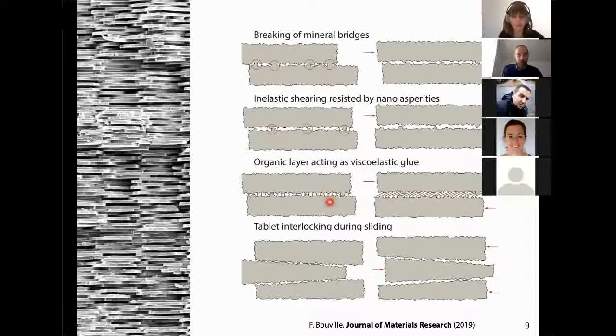And finally, if you look just at the interface, you also have this organic layer that will just act as a glue, right? And so in shear, you're going to have to shear the polymer, the protein layer as well, when you're trying to deform it. Finally, something that is also present in the structure and has been looked at is that it seems like there's an interlocking mechanism during sliding. So you can see that some of these platelets are dovetail shaped. And so when you try to move these platelets, you will also introduce some compressive stress that will further stop the propagation of the crack.